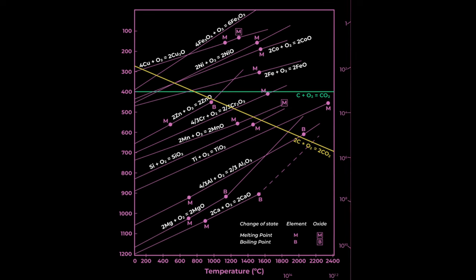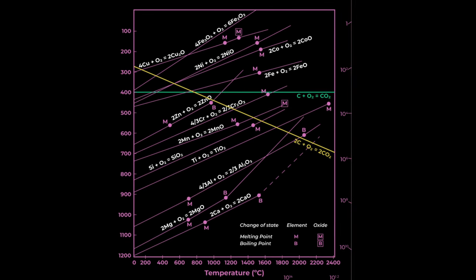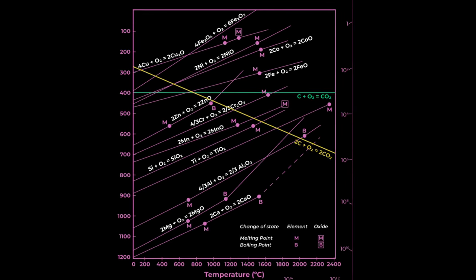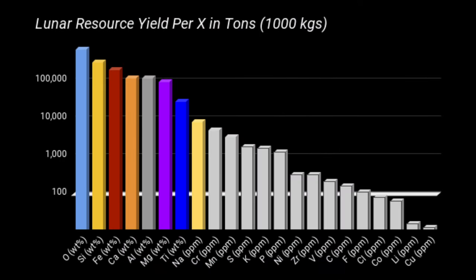How do we get our pure aluminum and silicon? Well, look again at the diagram. Calcium reduces everything, and we actually have a relatively large amount of calcium in our lunar regolith at about 7%, and no real uses for it now. So this got me thinking, why don't we just reduce everything with calcium metal by adding a bunch of it to each batch of regolith in a solar furnace, and then just electrolyze the resulting calcium oxide to yield oxygen gas and return our calcium metal for use on the next batch.